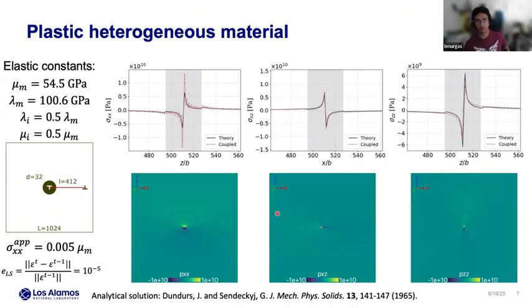Here, the effect of the boundary conditions will actually be higher if you have a smaller domain. That's why I'm using a 1024 grid, and every grid point has the dimensions of a Burgers vector magnitude, so it's about 2 Angstrom or something like that.